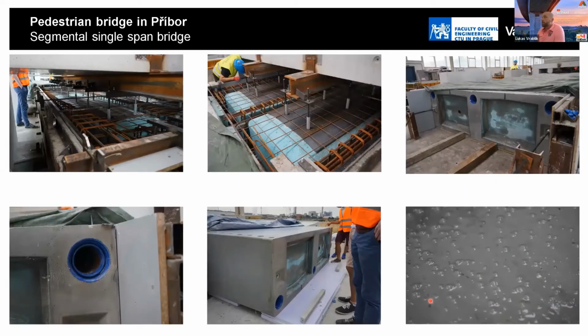Some pictures from the casting and production of the elements. We use a contact way to produce the elements. That means on one side, the previous segment makes a formwork, defining the shape of the sides for the next segment. You can see reinforcement and also the blue polystyrene members. As I said, it was a big challenge because during the casting, naturally the polystyrene elements want to go up. So it was necessary to fix them in the right position.